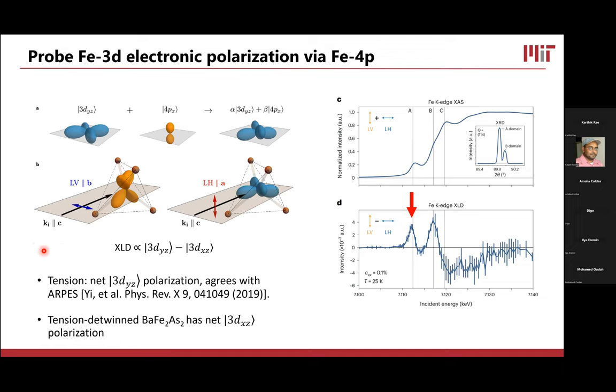So if you work through the details, you find that having a positive XLD for the orientation of X-rays in the sample that we have should correspond to having a net polarization of the 3d YZ orbital. And this actually agrees with the ARPES data that I showed you a few slides ago. So basically, we're on track for looking at the gamma point anisotropy of the iron orbitals.